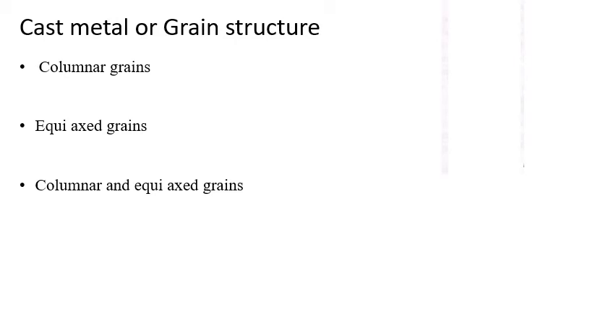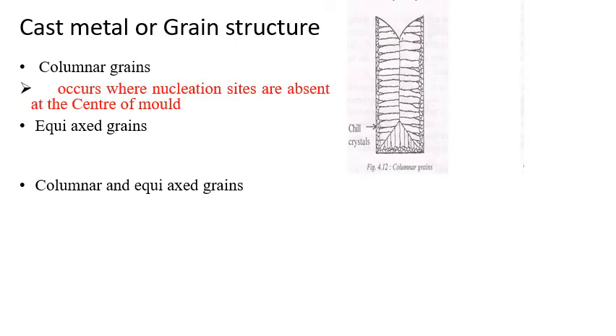So it again depends on the type of nucleation which is going to occur in a molten metal. If there are columnar grains, they occur where nucleation sites are absent at the center of a mold, which means the nucleation will start at the mold wall. So this is something like a heterogeneous nucleation, then the grains start to grow in this direction.